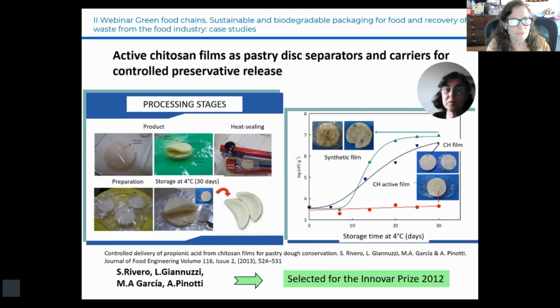In this case, films were developed using chitosan dissolved in propionic acid, a preservative used in dough discs known in Argentina as empanadas, a mass consumption product. These films were used as separators between the pastry dough discs, and their effectiveness in extending the shelf life of preservative-free dough compared to their synthetic counterpart was demonstrated. This work was selected for the 2012 Innovar Awards and was carried out in collaboration with Dr. Rivero, Pinotti, and Januzzi.